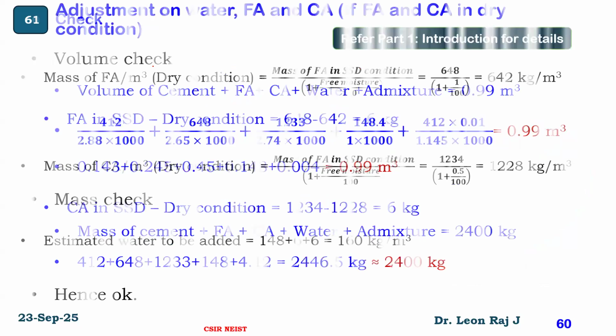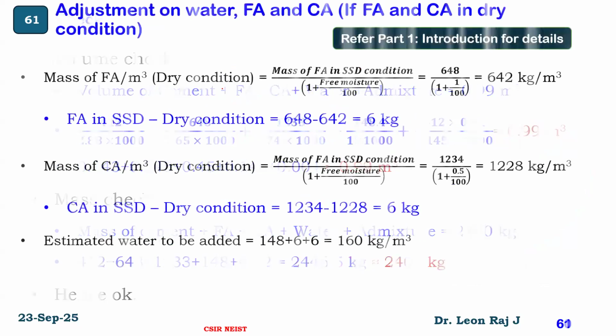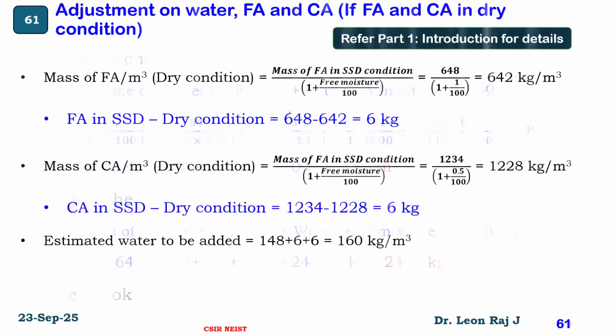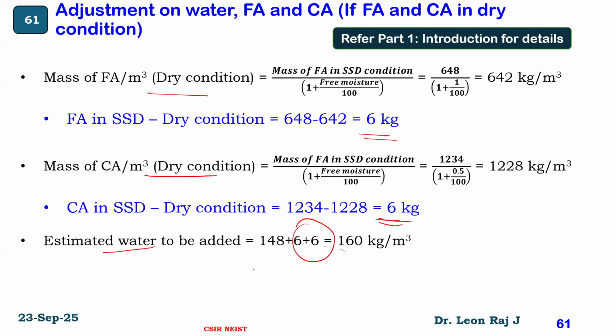Then for corrections for dry and wet conditions, here it is at a dry condition, so this needs to be subtracted. Once it is subtracted, you will get the corrected value for the fine aggregate as 6 kg and coarse aggregate also 6 kg. This 12 kg needs to be added as water to the estimated water content. Your estimated water content is 148, so this needs to be added to make 160 kilogram per meter cube, and in the remaining places this needs to be subtracted.